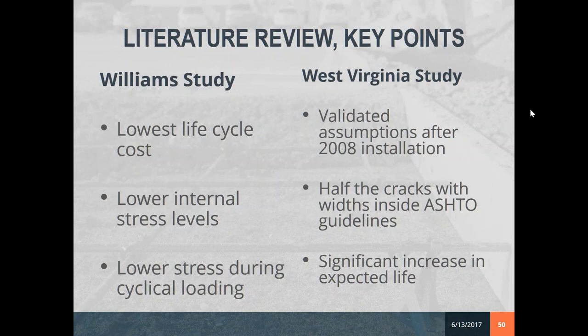There was a West Virginia study funded by the Federal Highway Department, where they paved half of a highway section with fiberglass FRPs and the other half with steel, to analyze crack spacing. With the steel, the cracks showed up approximately every 3 feet. With the FRPs, they were about every 7 to 8 feet. It's a little bit wider crack, but it was within the allowable tolerances. When they removed pavement sections on both, the steel had already started to deteriorate, whereas there was no deterioration in the fiberglass section.